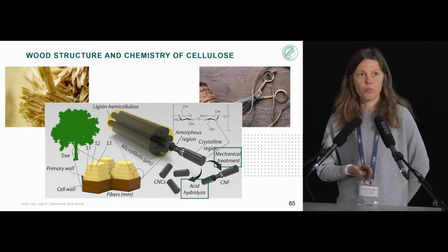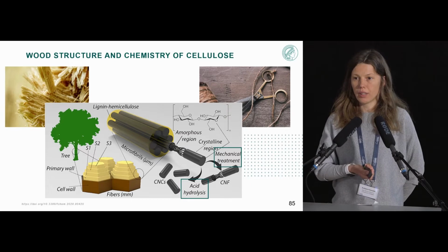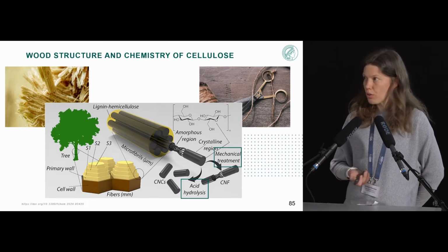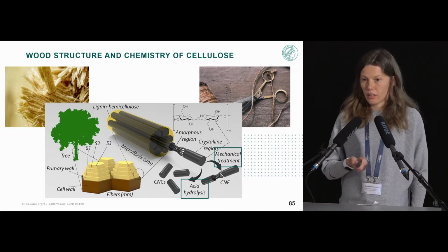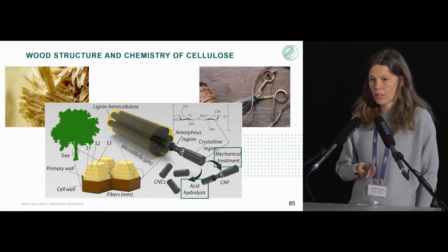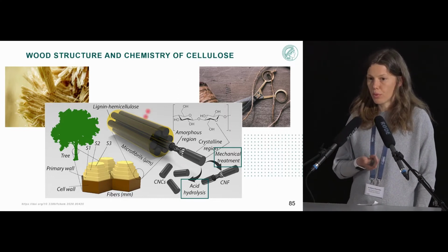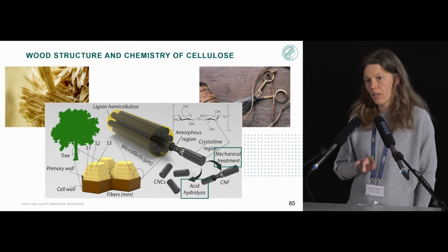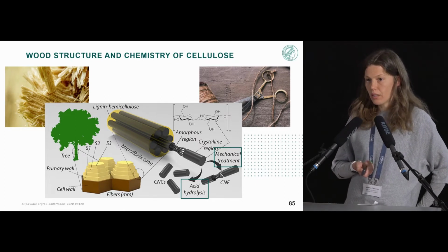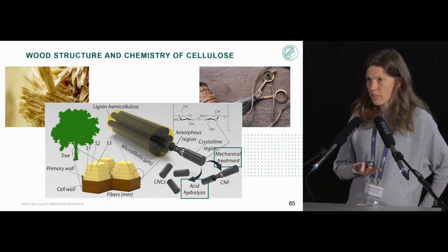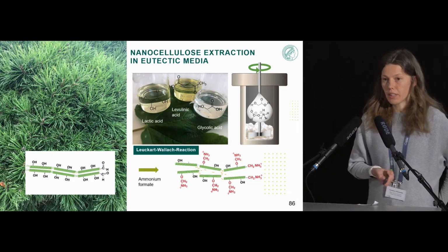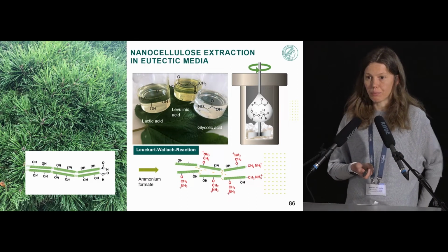Just to be on the same page with everyone, this is how cellulose nanocrystals are extracted. Their extraction is basically based on the different kinetics of the reaction between amorphous regions and crystalline regions, and, well, partial functionalization of the crystals. This is done with acidic hydrolysis, and can be done also with the same Leuckart-Wallach reaction. And this is exactly what I did with the cellulose.